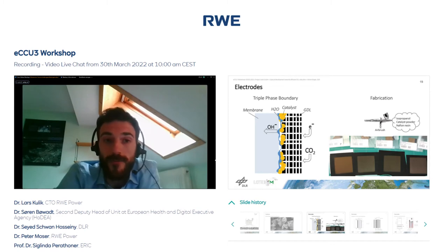So we have this mass balance, allowed for the mass balance. And a problem here is, for instance, if one of these phases is dominant, for instance, water comes here and floods the catalysts, this will be a problem and we have less performance. So triple phase boundary is one of the key performance indicators to have a successful electrode.